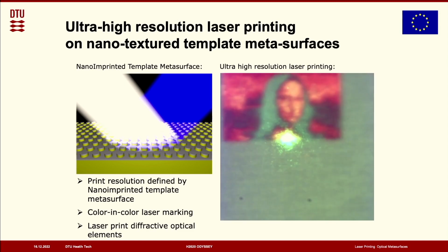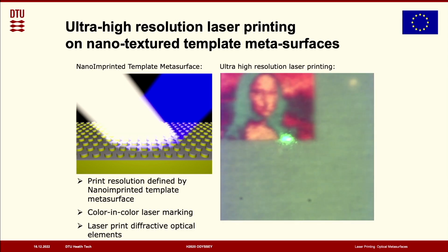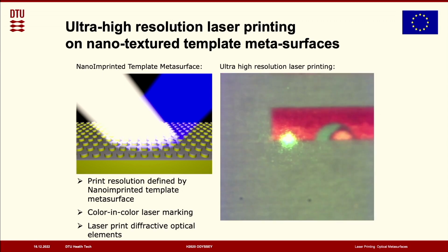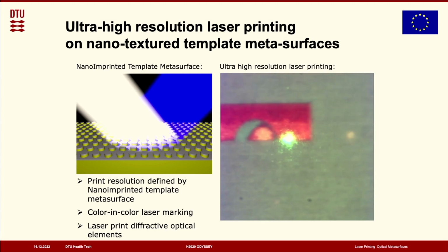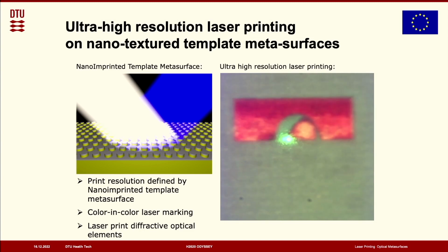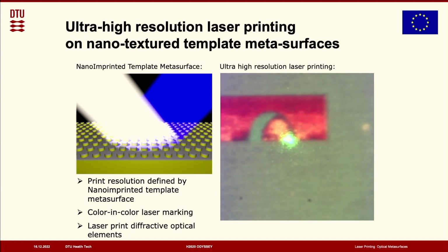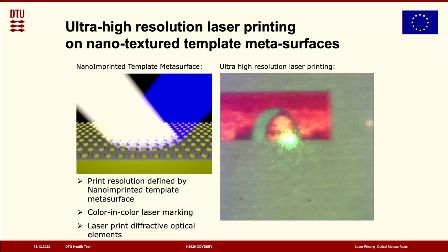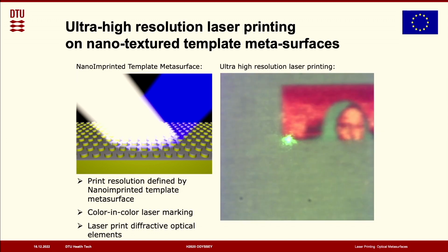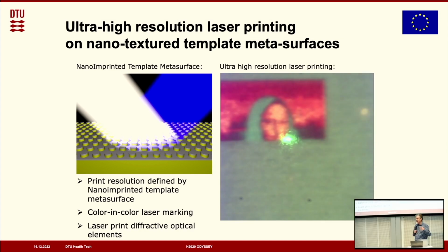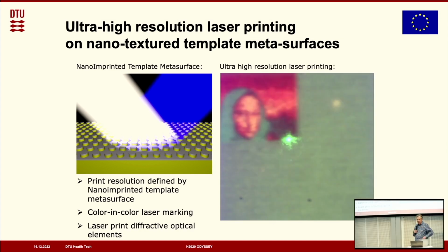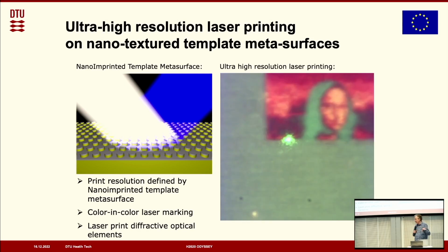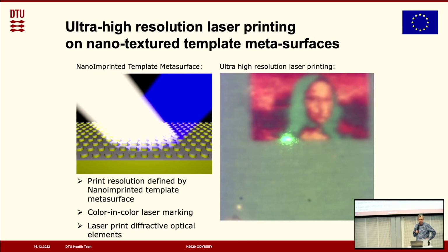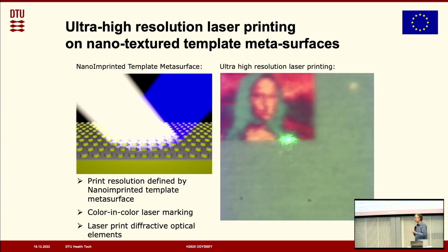And then it turns out that the green laser light is absorbed very, very efficiently. So we have a very efficient, energy efficient transfer of energy from the light, so to locally melt the material and ablate the material, heat it up. And this is illustrated in the movie to the right, where you can see the laser spot, and then we are scanning with this metasurface underneath, and you can see that by changing, or modulating the power of the laser as we scan, then we can print different colors. So this is our laser printing of those metasurfaces.